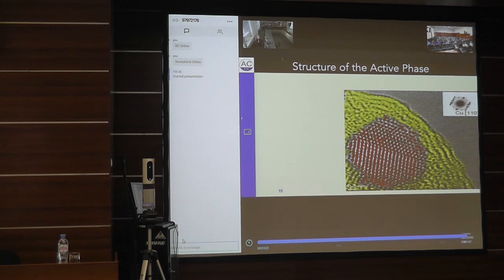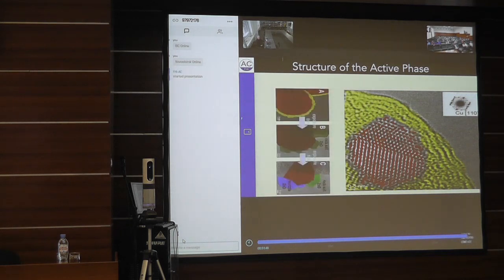And you ask yourself, how can this be active if it is completely encapsulated by zinc oxide? There are two possibilities. Either the CO2 migrates through pores of the zinc oxide that we cannot see, or the zinc oxide is not covering the particle as a whole under operation conditions. It is dynamic. And what we see here is the frozen state of the system. The first indication that this might be true is if you look at the stability of the thing. If you are not very careful with your electron microscope, then you destroy this zinc oxide overlayer and you form this coexistence of crystals, but that is a beam artifact, that is not the true state of the catalyst.